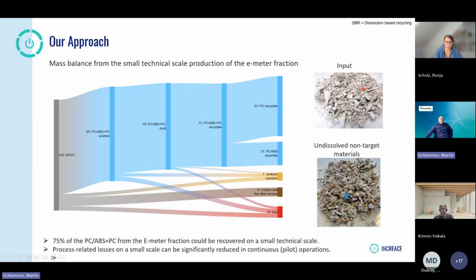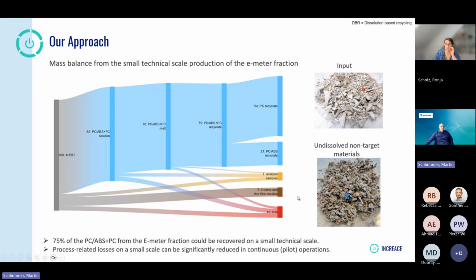Looking into the overall mass balance of this dissolution-based recycling, exemplified for the E-meter fraction, you see that the overall output is quite reasonable. You have something like 75% coming out as either PC recyclate or PC ABS. There's some others going out for sample analyzers. There are the coarse and fine residues. And as always, if you work with lower capacities, you face the loss issue, which may sometimes be just water, sometimes losses to any kind of surfaces. So a very typical one here.